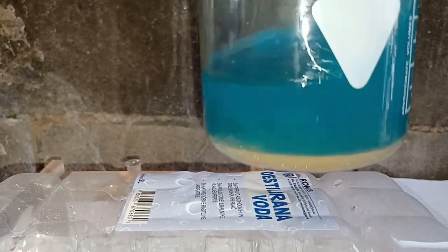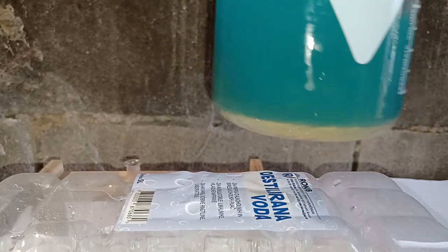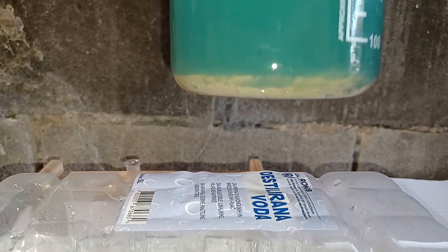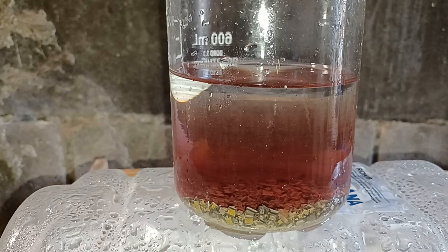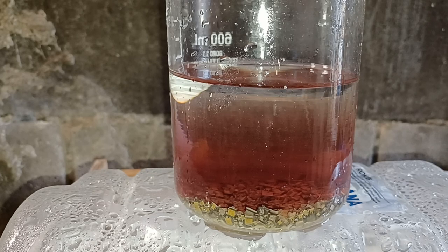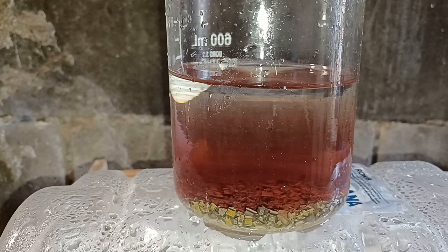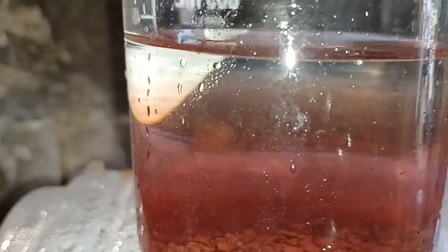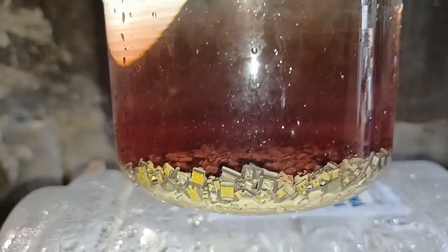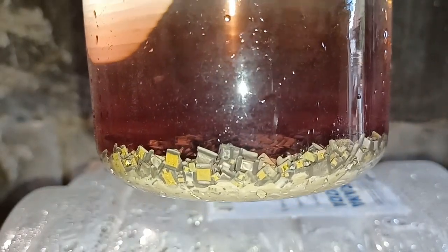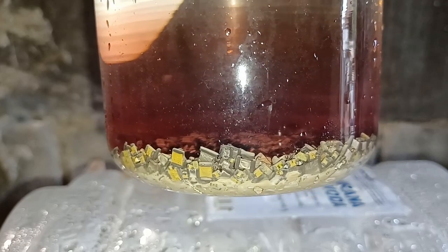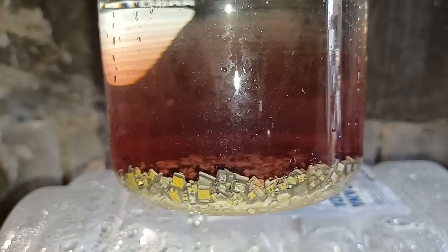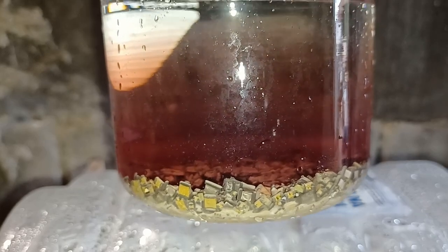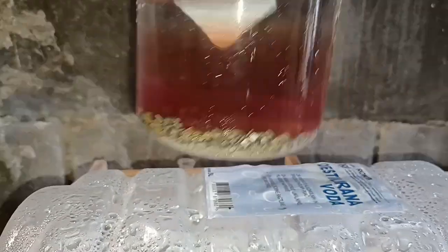Ceramic began to break down very fast, and the solution turned greenish blue color. After 24 hours, the color is a striking reddish pink that is, interestingly enough, somewhat stratified, less intensive at the top of the solution. As you can see, some of the capacitors dissolved to the internal electrode. I'll stir the solution a bit and let it sit for another day. So far, the approach seems to be working.